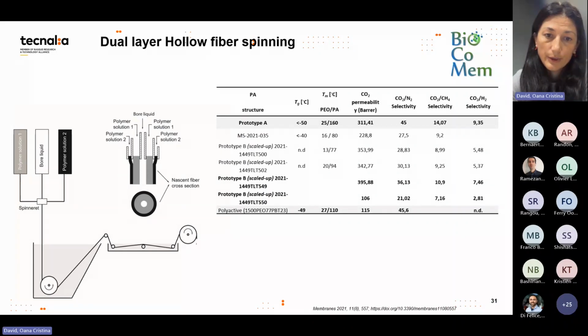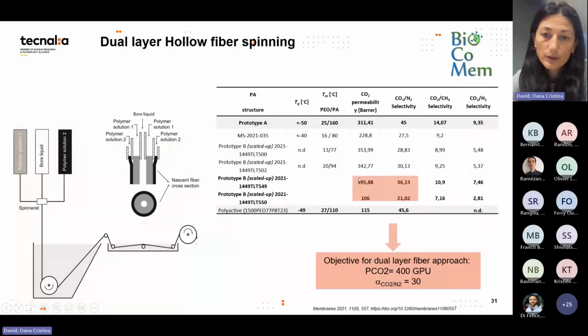And then we have Arkema scaled up 2 new polymers. The second, TLT 550, was the one for the support layer, with more polyamide part. And TLT 549 had an even higher polyethylene oxide part, so it even had higher gas permeability to carbon dioxide. So with these values, we assume that if we have this